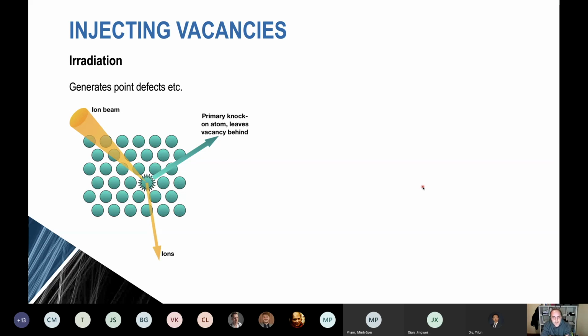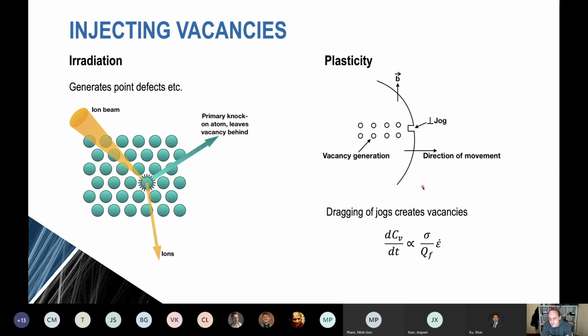But another very interesting way to give some mobility to materials is actually use plasticity. Now, in FCC materials like aluminium, our dislocations contain a certain concentration of thermal jogs. And when the dislocations move through the material, the dragging of those jogs leads to the generation, it's a purely geometric effect, the generation of vacancies. And so plasticity generates vacancy, actually then generates interstitials as well. But in this case, we're particularly interested in the generation of vacancies. And that dragging of jogs to create vacancies can lead to the development of a non-equilibrium vacancy concentration. And these vacancies can be used to mediate mass transfer.